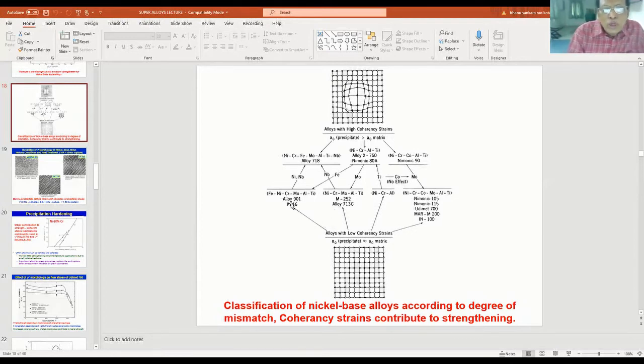For example, you take a superalloy which is known as Inconel 706. It is not a nickel-based superalloy, but we call it an iron-nickel-based superalloy because these are the two elements which form the base, and both of them combined together. Nickel is 44, iron somewhere 37 or something like that. They combined, they cross 50% weight percentage, which qualifies them to be a base. So this is an iron-nickel-based superalloy for which chromium is already added. Molybdenum is added for introducing solid solution strengthening at elevated temperature. Aluminum and titanium have been added to produce the gamma prime. That is the way, when this composition has been developed, it is forming a gamma prime with low coherency strains.